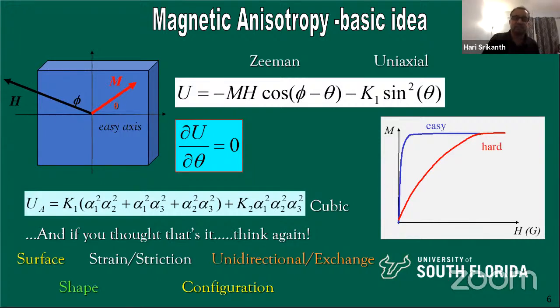So we can represent this by the total energy here as a combination of two terms. One is the Zeeman energy, which is due to the external field. That's this first term right here. And the other one is, in this case, a very simple uniaxial anisotropy. I'm just saying that there's a preferred direction. And that is the anisotropy energy. So you can see that the total energy and essentially the equilibrium position of this magnetization vector is determined by minimizing this. And you know how to minimize this, right?